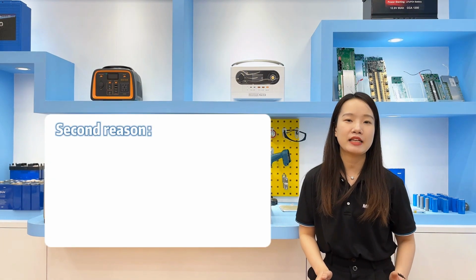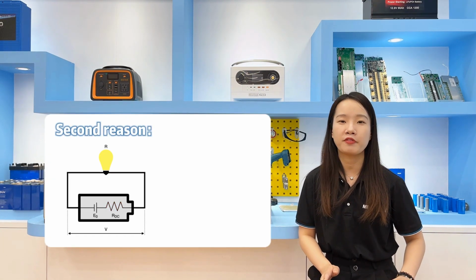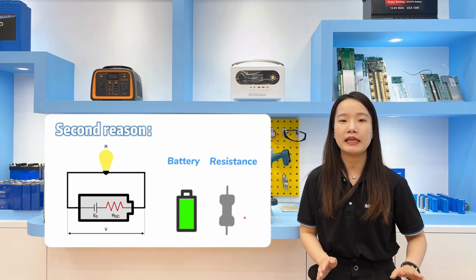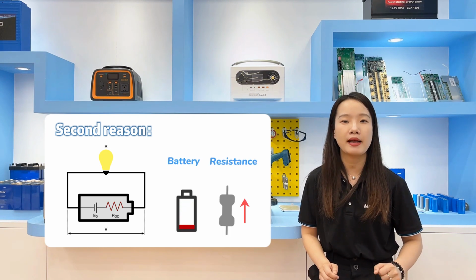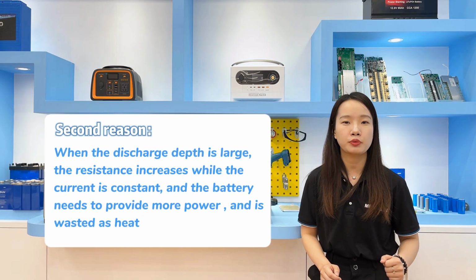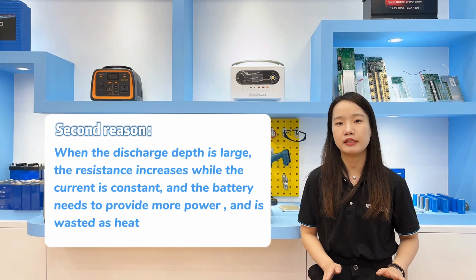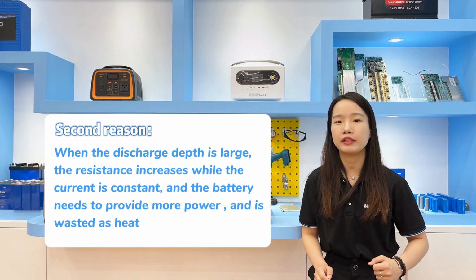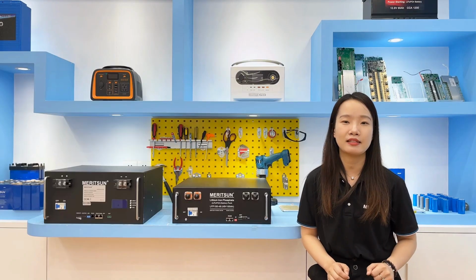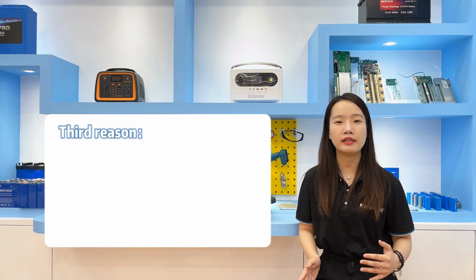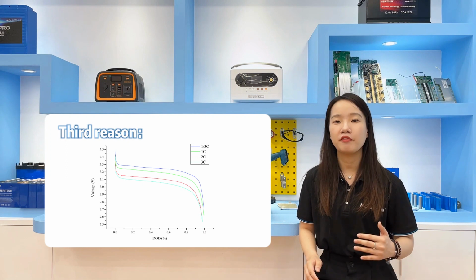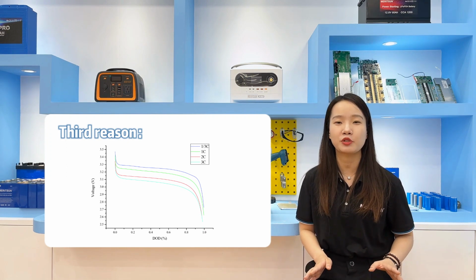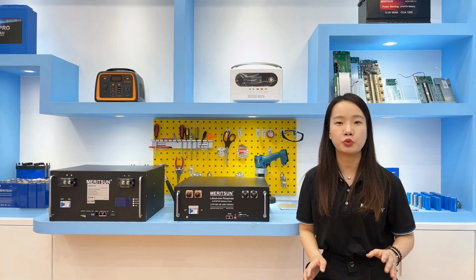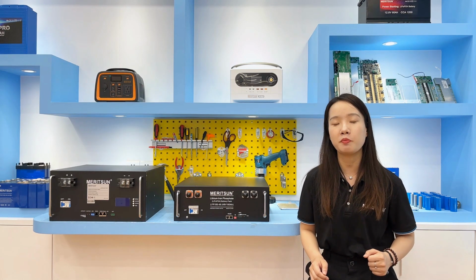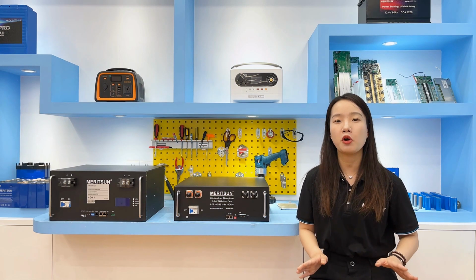The second reason is that when the battery provides a certain amount of current to any electrical appliance, the internal resistance increases while the battery capacity decreases. When the depth of discharge is large, the internal resistance increases while the current is constant, and the battery needs to provide more power and wastes it as heat. The third reason is that the originally relatively stable discharge curve of the battery will change sharply when the depth of discharge is large. Therefore, limiting the depth of discharge to a relatively flat range can enable consumers to have better control over the power. You also can get a better user experience and a better battery life.